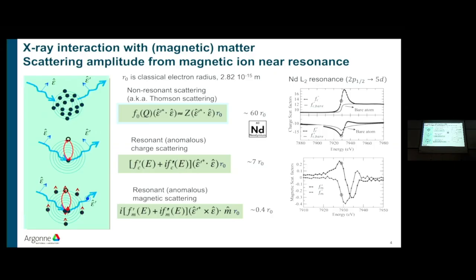How big is it? You see here, and these are the scattering factors at the neodymium L2 resonance. I'm just using neodymium as an example. It is 0.4 R0. So whereas the non-resonant charge scattering was 60, the resonance charge scattering was 7. The magnetic resonance scattering is 0.4, so less than 1% of the charge scattering. So it's a very weak effect.